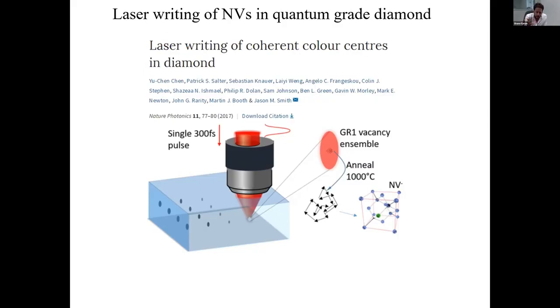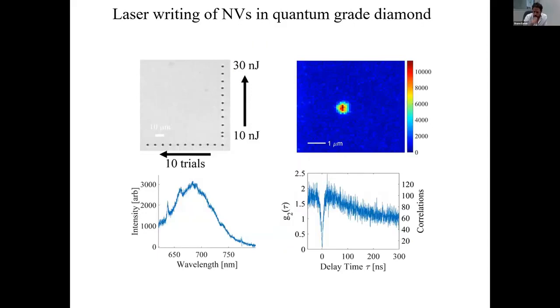And when they encounter one of these very rare nitrogen impurities within the diamond, again, you can design this so that you have the correct purity concentration you'd like to achieve single NV centers. They found that with a 50% success rate, they could achieve single NV, single photon sources with this technique. And we indeed showed at the very same time, they published their work, of course, in Nature Photonics. We showed a couple months later, a much similar result.